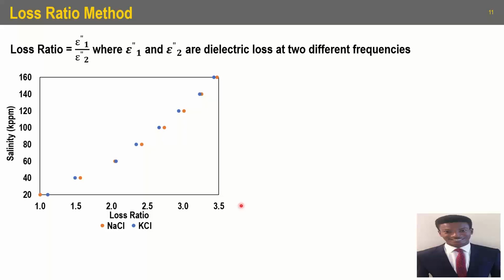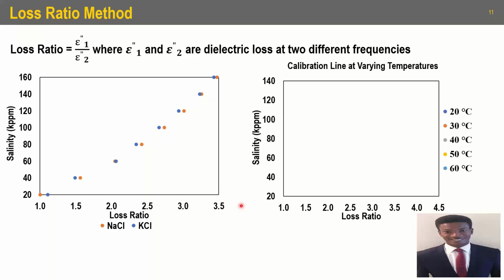And then based on this, we can go ahead to use this calibration line at different temperatures to infer probably what the salinity would be in the subsurface. And here we see the salinity as a function of loss ratio at 20 degrees Celsius, 30 degrees Celsius, all the way to 60 degrees Celsius. So depending on the temperature, you can infer what the salinity would be based on knowing the loss ratio.